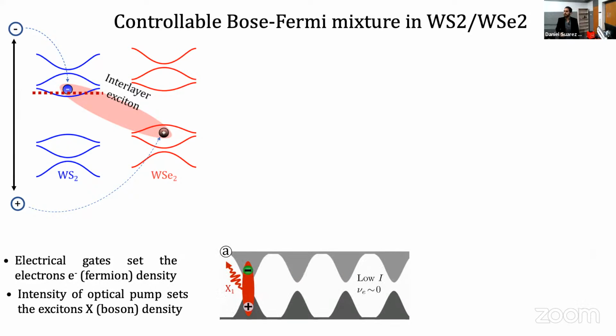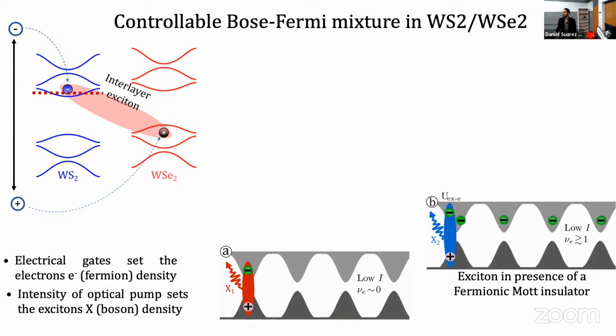Then the interplay between these two parameters can give us interesting situations. For example, we can start from an empty lattice with very few excitons, just to have some optical signal that we can detect. But if we increase the doping level, so we dope our system with electrons, we can achieve the Mott insulator state. And this exciton is not going to be in an empty lattice anymore, but in a completely occupied lattice of electrons. Then the optical properties of this exciton are going to be modified because it has to overcome the on-site repulsion, and the energy of the exciton is going to be modified.